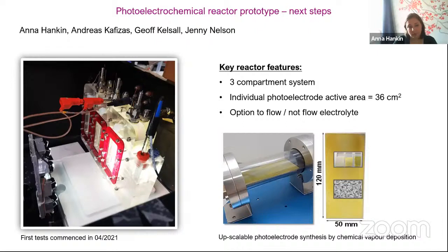So we're going to measure gases, we're going to flow electrolyte, or not flow electrolyte, and compare the influence of hydrodynamic control on performance. We're simulating optical losses in the system as a result of bubbles, as a result of all the different layers that you have. We're going to do this at first using bismuth vanadate photoanodes and an externally mounted PV. But the idea is to develop that further into a purely photoelectrochemical system, so photoanode and photocathode and no PV. Experiments have literally just started about a month and a half ago and are only quite limited.